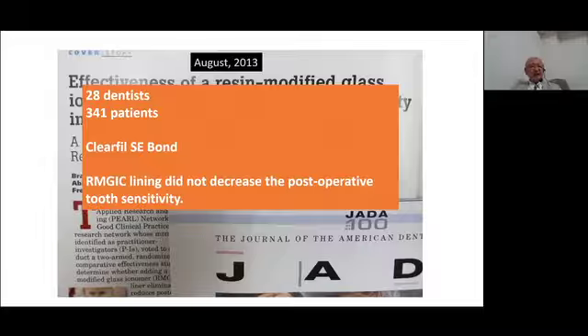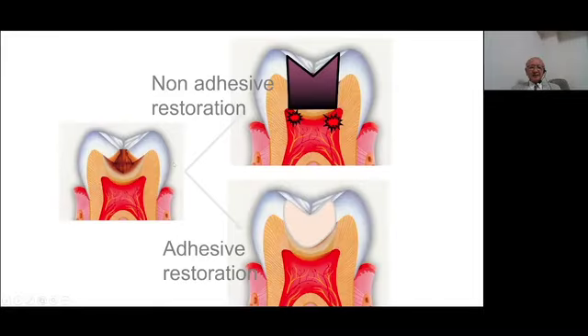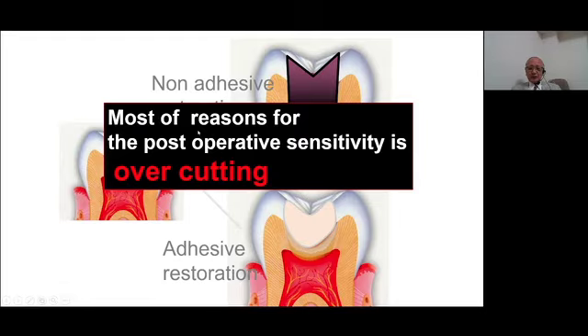The result was very simple. Resin modified glass ionomer cement lining did not decrease the post-operative tooth sensitivity. That's why the author of the paper recommended not to apply the lining material. In the case of adhesive restoration using this kind of excellent adhesives, we don't need the lining material. So this is the big difference between the adhesive restoration and the non-adhesive restoration. Now I can say that most of the reasons for postoperative sensitivity is overcutting of the sound dentin. Now I hope you can reduce the prevalence of postoperative tooth sensitivity after the restoration.